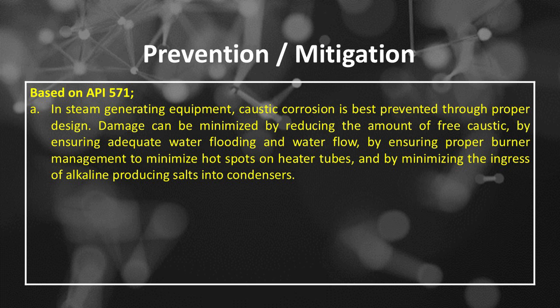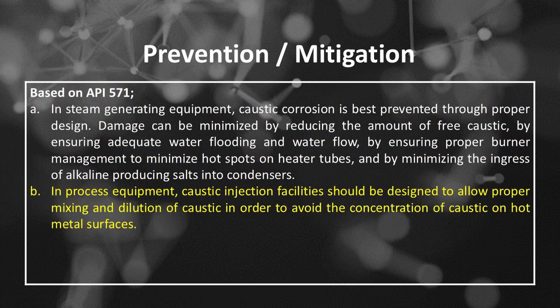Caustic corrosion damage prevention and mitigation based on API 571, Number A, in steam generating equipment, caustic corrosion is best prevented through proper design. Damage can be minimized by reducing the amount of free caustic, by ensuring adequate water flooding and water flow, by ensuring proper burner management to minimize hot spots on heater tubes, and by minimizing the ingress of alkaline-producing salts into condensers. Number B, in process equipment, caustic injection facilities should be designed to allow proper mixing and dilution of caustic in order to avoid the concentration of caustic on hot metal surfaces.